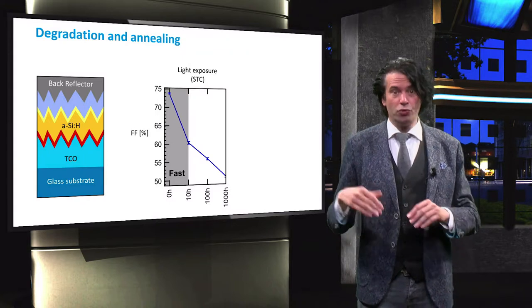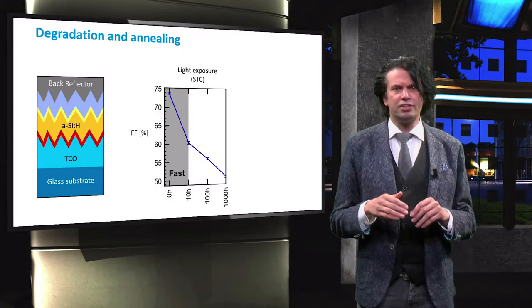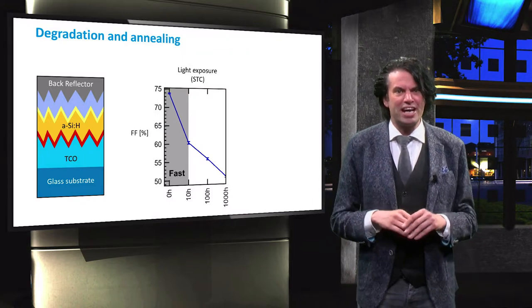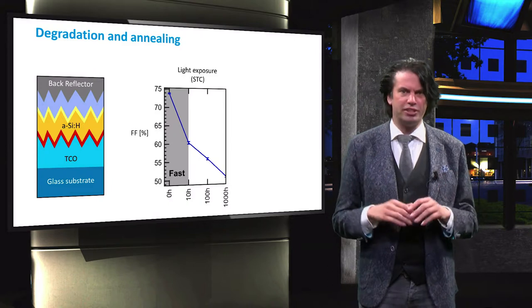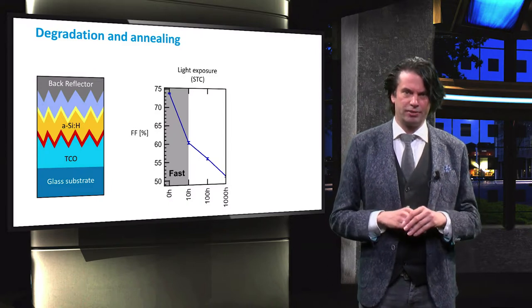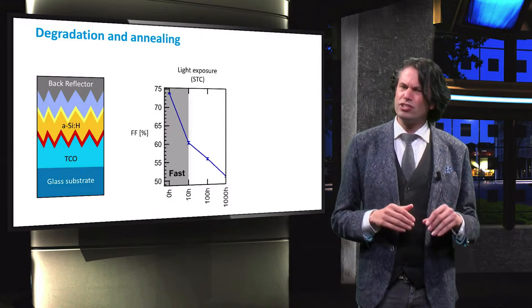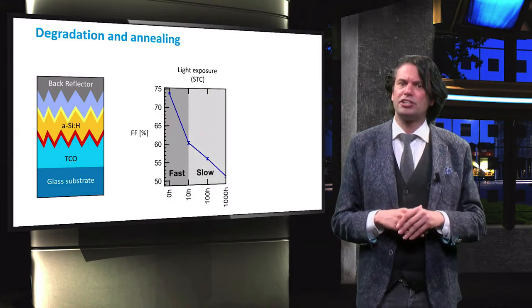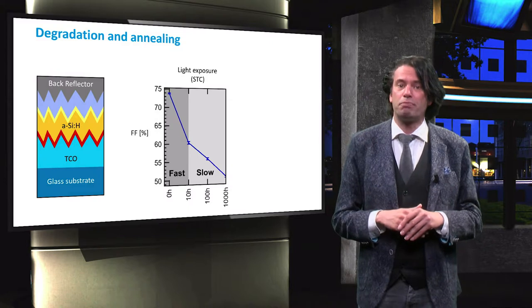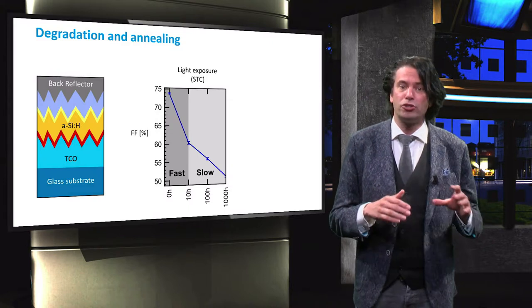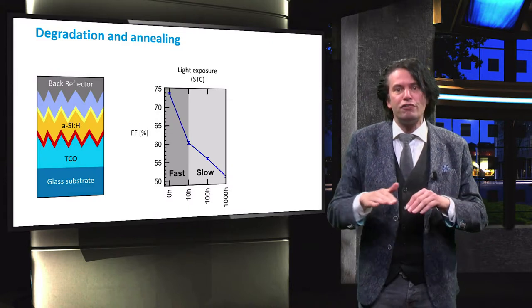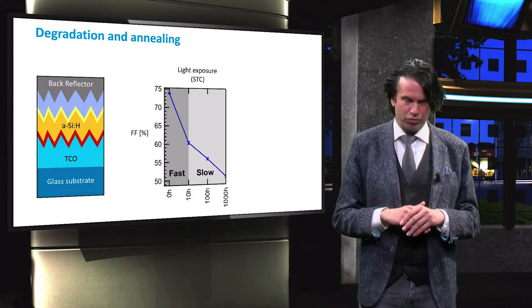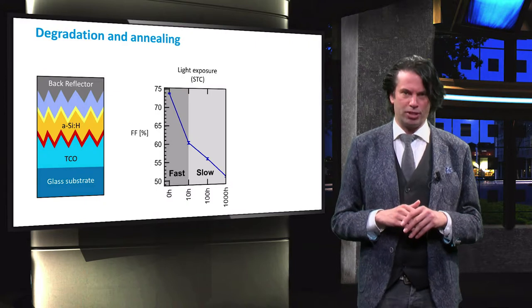From 10 hours onwards, the cell degrades further but at a reduced degradation rate. In this slow region, the fill factor decreases an additional 9 percent absolute to achieve a stabilized fill factor of about 51 percent.